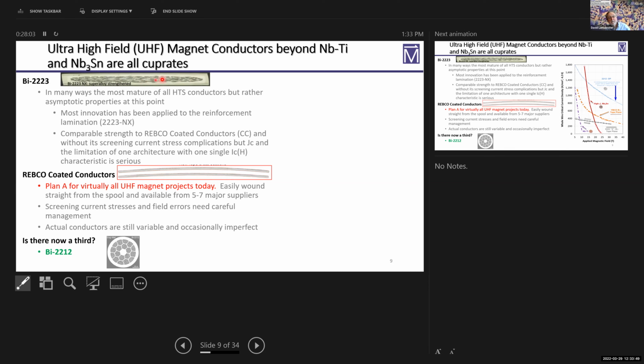But people found that the critical current density was much, much higher when they rolled it into tape, because the crystal structure is anisotropic, and this essentially gave a much better alignment of the crystals and therefore gave a higher critical current density. And it's interesting, this is the most mature of all HTS conductors, but frankly, its properties are just asymptotic. It's difficult to continue to improve it. But on the other hand, they have a very mature process. It's made by a company, Sumitomo Electric in Japan. And you can buy it. You can buy it in kilometer lengths.